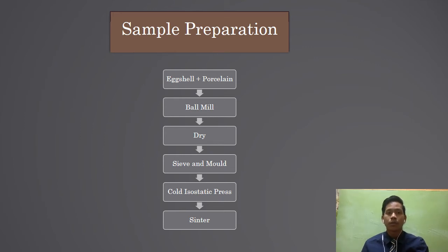And then the obtained slurry form of the mixture will be dried at room temperature for 48 hours. The dried powder will be sieved to obtain a particle size of less than 63 micrometers. The powder will be filled in a mold and pressed using a cold isostatic press and sintered at temperatures of 1200, 1250, 1300 and 1350 degrees Celsius.